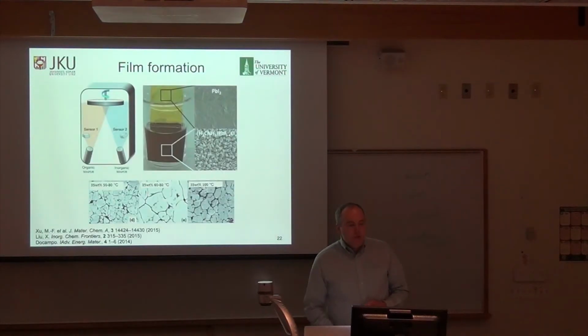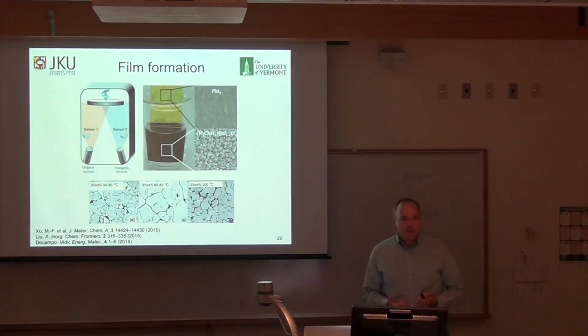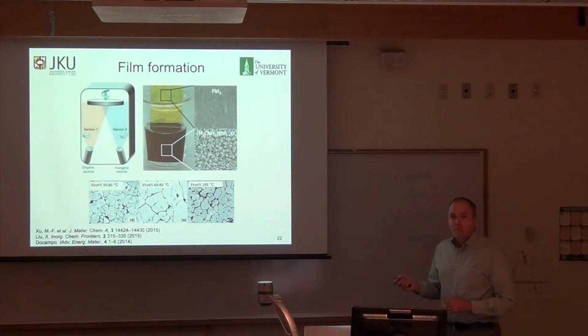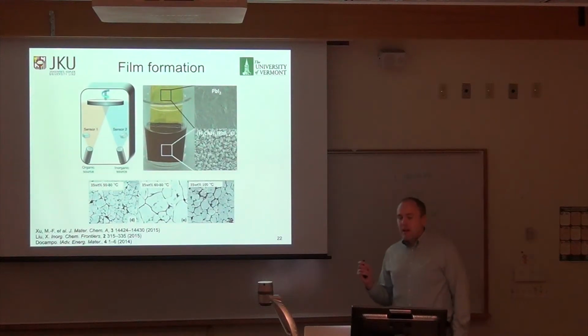So what's wrong? What problems still need to be solved? One is film formation. You can process these from a vacuum source — pump down a chamber, heat up two sources, one with methyl ammonium, one with lead iodide, and co-deposit them onto a substrate. You can make pretty nice films this way, but once you reach a certain critical thickness, they start to crack and form non-continuous films. With solution processing it's even worse — there are ways to fine-tune it to get a nice film, but once it gets too thick, it starts to crack.